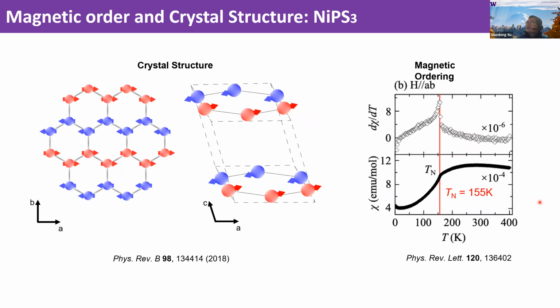So let's start with the focus of the first part of my talk, which is nickel phosphotrisulfide. Here I show the spin structure in the top view. You see all the spins are aligned in this direction, which we define as A, and orthogonal to this zigzag direction is B. If I look from the side view, the spin is mainly aligned in the plane, but a recent neutron scattering study also shows that the spin has a slightly tilted angle out of plane. This is still, I think, an ongoing study. It's not settled. But for this talk, we can basically consider the spin is aligned in the plane here.